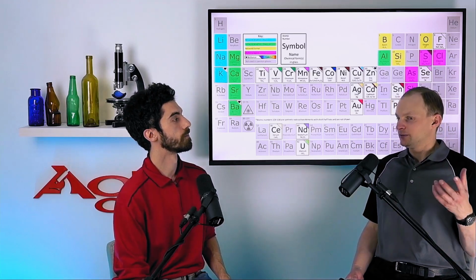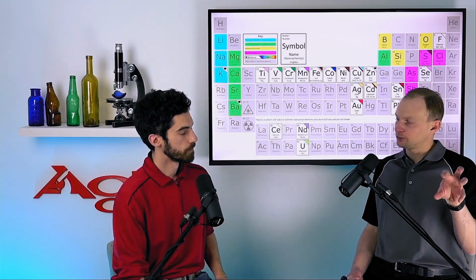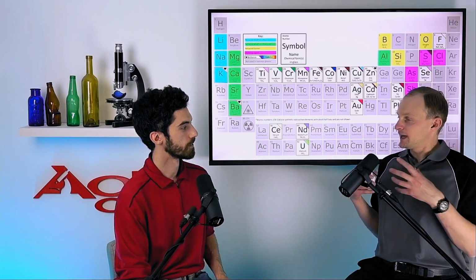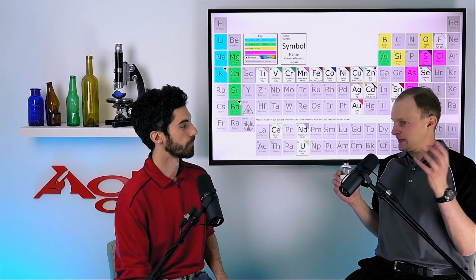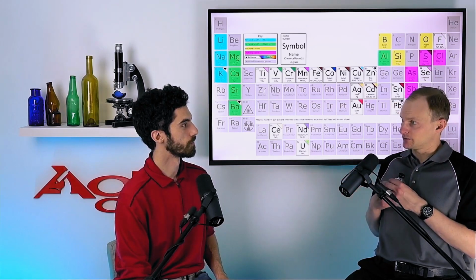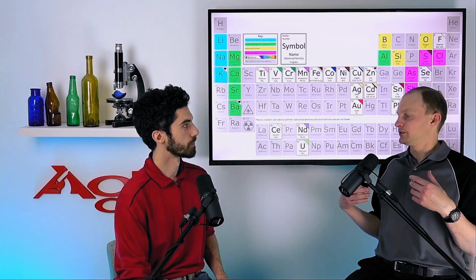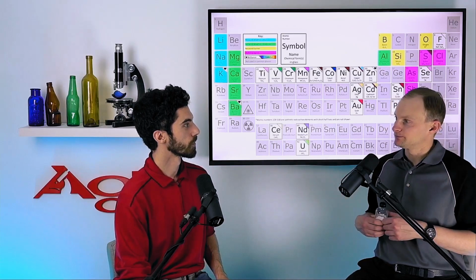Now it is making it less chemically durable. So we don't just have silicon and oxygen bonds in there. Now we've got silicon, oxygen, and some sodiums interspersed, and this particular glass could be attacked by water in the environment. So if we just had soda and silica, you can make glass, and that product is called water glass. We use that in different types of metal industries, but that product wouldn't be any good for containers because it's water soluble.